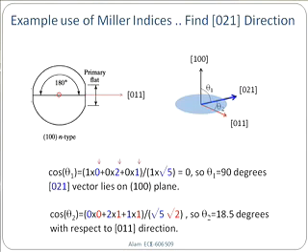Now, in this case, we were lucky that the vector turned out to be in the same plane as 1 0 0. If the angle was, let's say, 85 degrees or 120 degrees, then you would have to saw the wafer at an angle to define that 120 degrees and then rotate it along. And so therefore, at the end, you will determine that 0 2 1 is at 18 degrees with respect to the primary flat, and you will create your wafer or your device there, shown here in the blue patch, and your advisor will be very happy.